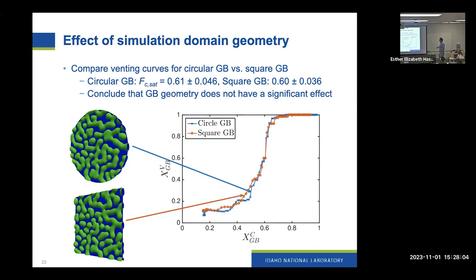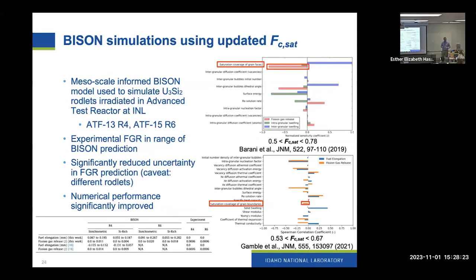And we see that the release fraction, the progress of venting, is very similar for those two different simulation domain geometries. So we don't think that grain boundary geometry has a really significant effect. That gives us more confidence to use these values. And ultimately, what we're trying to get to here is something that's useful for Bison.